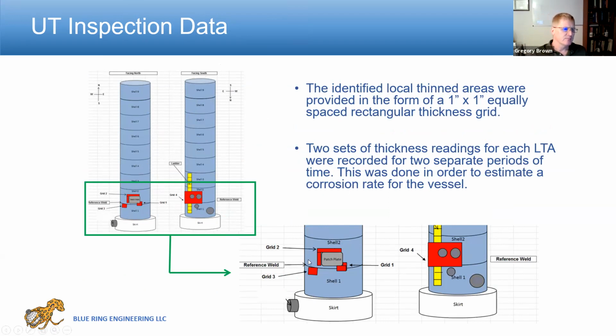A couple of these areas were around a patch plate where a repair was done previously. A region of the vessel was cut out, and then a new piece of metal was put in. So some of that damage may have been due to overheating or material damage that led to corrosion around that patch plate. So you can see these grids 1, 2, and 3 kind of near that patch plate.